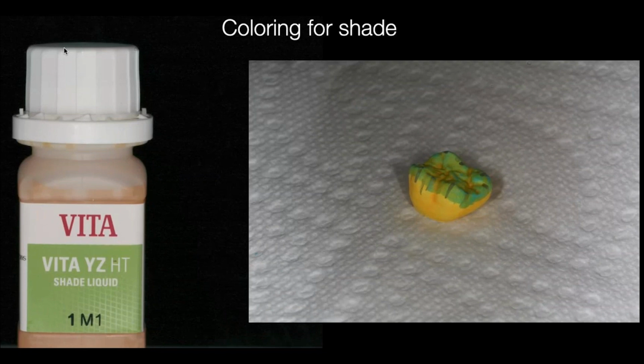Now, in the original days, we used to color the zirconia, and most of the top ceramics out there that don't really like the pre-shaded zirconia, they still do this. They still paint it, and you know it's a little bit more work. I call those avatar crowns. They look beautiful, and Enrico Steger and all those people at Zirconzahn started all this, and they really are masters at it. So the whole idea is if you can't get the color from a pre-shaded puck, you're going to have to color it. The one drawback